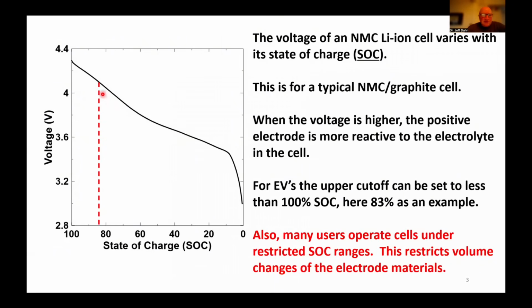And what I'm showing here is a battery that's charged to 4.1 volts, which would be about 80% state of charge. Here's an example. And in addition, it's common, as every EV user knows, not to discharge all the way to zero. You might discharge for 20% or maybe for 38% over these type of restricted state of charge ranges. And there's reasons for doing this from a convenience point of view, but also when you do this, it restricts the volume changes that take place in the electrode materials, and that can prolong battery life.